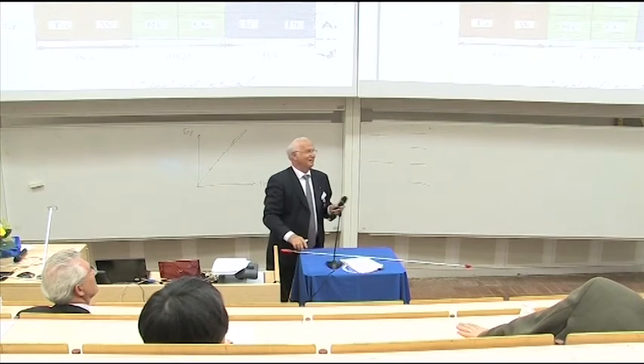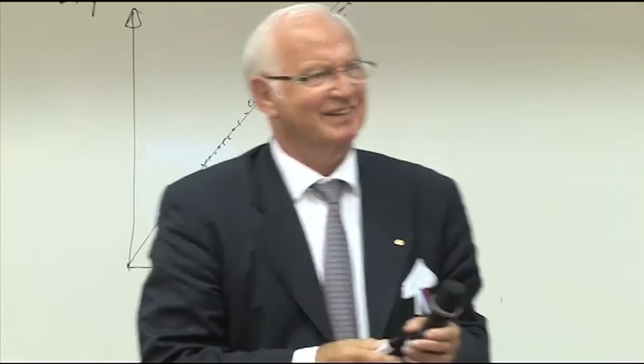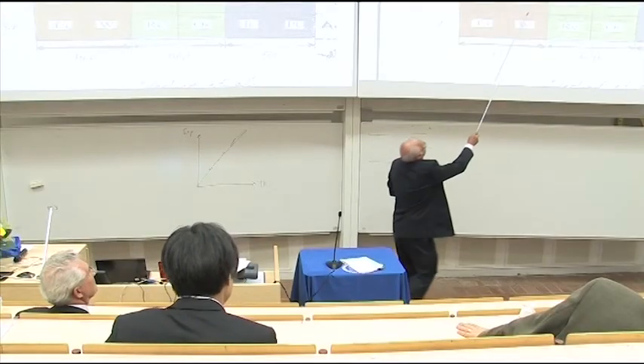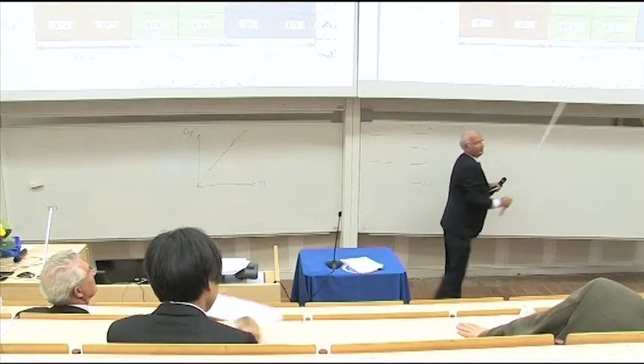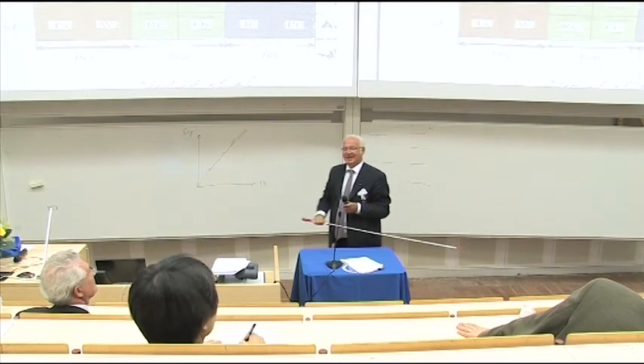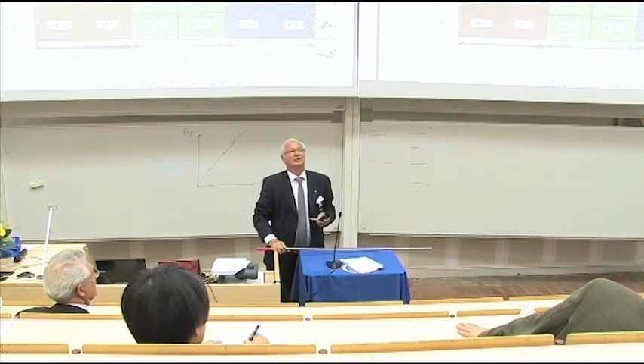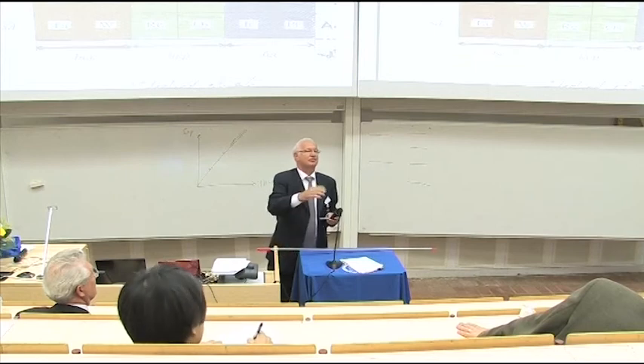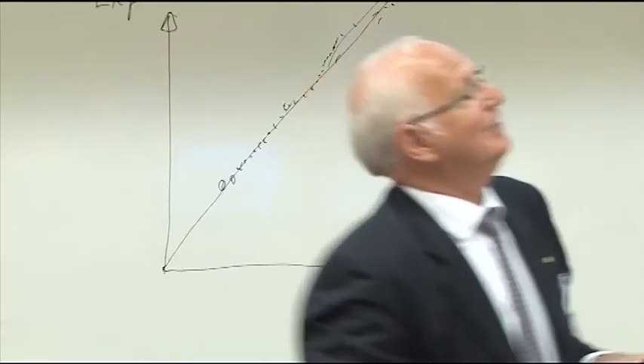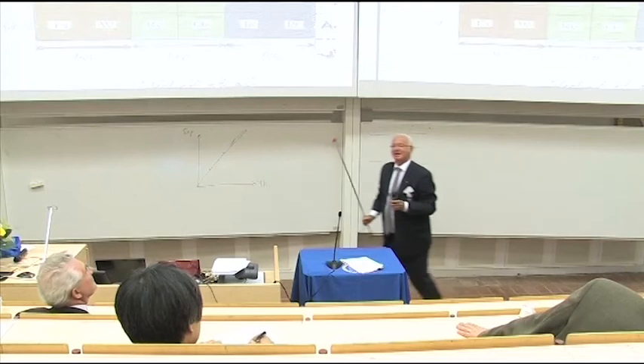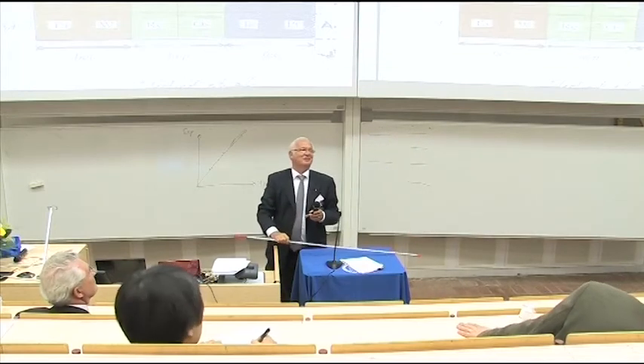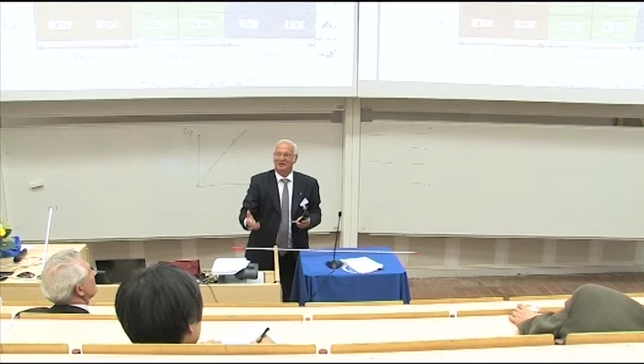And you know this pair. We did this already in 96, 8, well, anyway. And the funny thing is that you can look upon various alloys, and you can also determine the critical concentration when they go from one phase to the other. And you compare the similar transition if you do it between iron and cobalt. Same numbers. It works almost too good because we know it's not fully true.